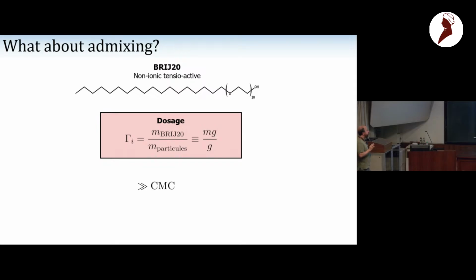Okay. So I will just mention an evolution of this problem, because that's motivated by the experimental problem of cement, where people often use polymers. They introduce polymers, and the theory in the field is that you add polymers that prevent contact. But if you prevent contact, you lose adhesion, and if you lose adhesion, probably you sediment because it's not density matched. But they don't want it to sediment. So we think that even at the dosage of polymers that are used, they don't prevent adhesion.